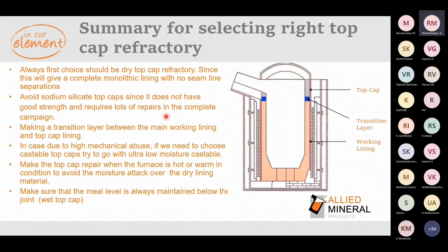These are two different products, two different product lines, and the merging will not always be proper. You will always have a small seam line separation, which gives the metal a way to penetrate inside. So we always recommend dry top caps, like what I talked about: fused silica based, or normal silica based with high % boron oxide, or fused silica based with stainless steel fibers. And we ask our customers to avoid sodium silicate top caps, since they do not have good strength and require a lot of repairs in the complete campaign.